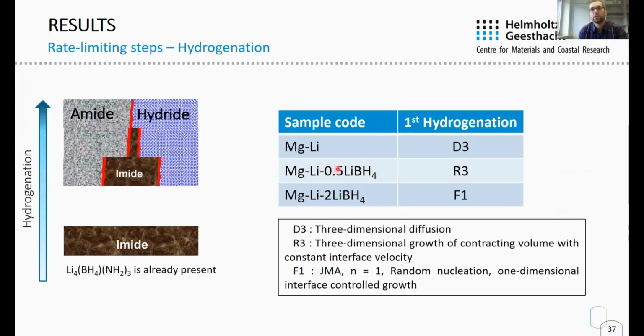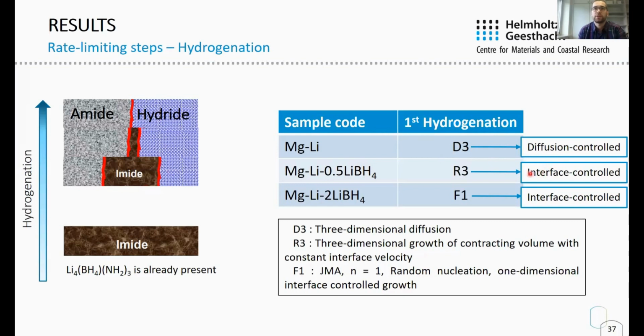The first hydrogenation kinetic behavior of the samples showed that depending on the lithium borohydride stoichiometry, the rate limiting steps are changing. The reaction rate of the pristine sample is controlled by a three-dimensional diffusion model. This kind of mechanism usually occurs for several hydrogen forming materials. Considering that this is a multi-component system, it's possible to relate the diffusion control mechanism to the slow mobility of the species upon hydrogenation. Additive containing samples show interface control mechanisms. We know that the reaction kinetics of these samples are much faster. Therefore, this change can be attributed to the presence of highly ionic conductive Li4BN3H10.